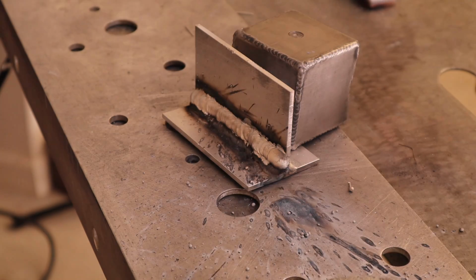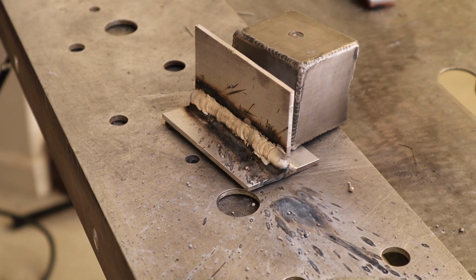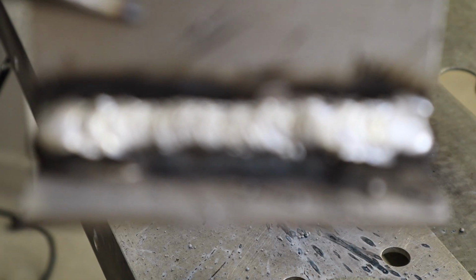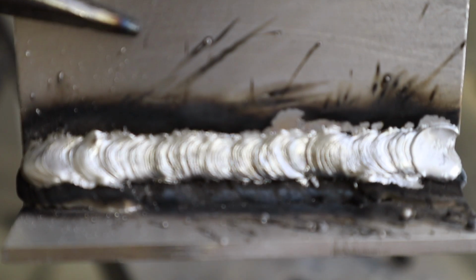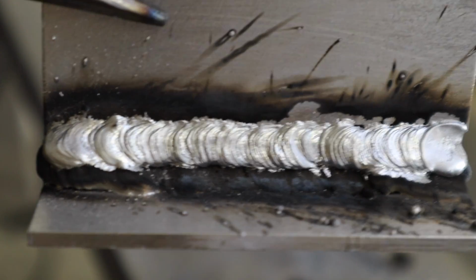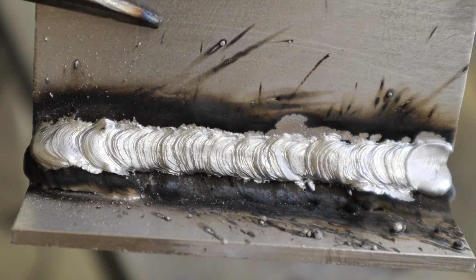Then I switch over and I try the manual settings. 18 volts, 12 meters per minute. But you heard that little whistle sound, and then I was able to continue. When I hear that, I just tried to increase my stick out slightly just by positioning the gun, and it prevented it from burning back to the tip to where it stopped welding. Again, not a bad looking bead for first time around.